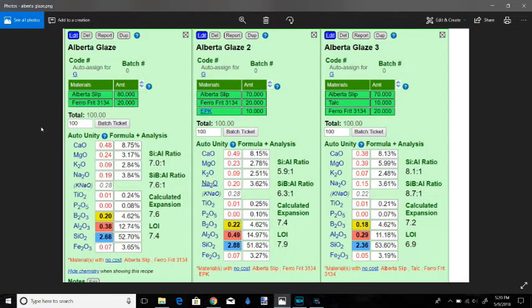Alberta slip is another great sourcing material for your glaze. Like, for instance, right here, 80% Alberta slip, 20% Frit 3134. Here's the calculated mathematical configuration for what it would look like. If I add EPK, the levels of alumina and silica have increased, as you can see right here. And then with the introduction of talc, as you can see, magnesium oxide is increased compared to here and here.